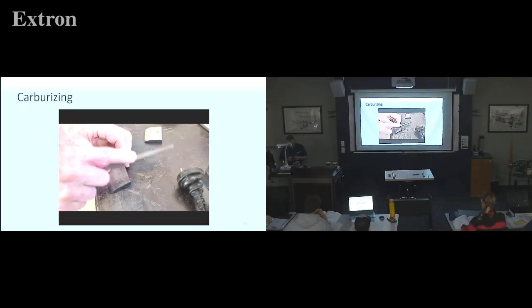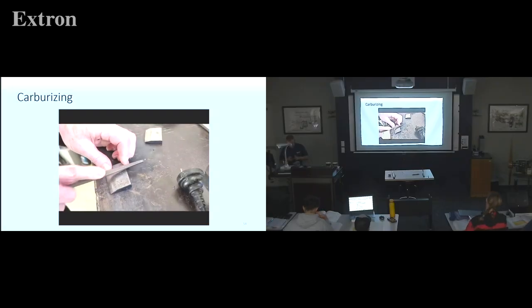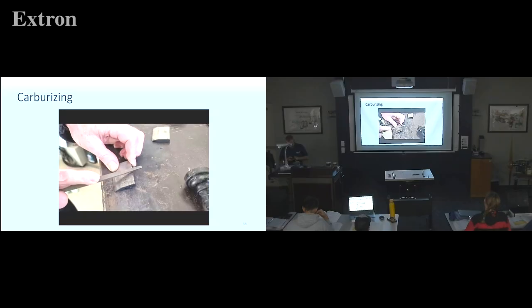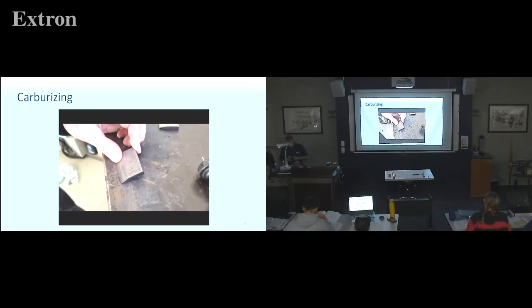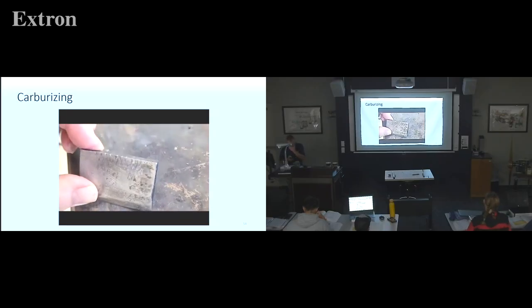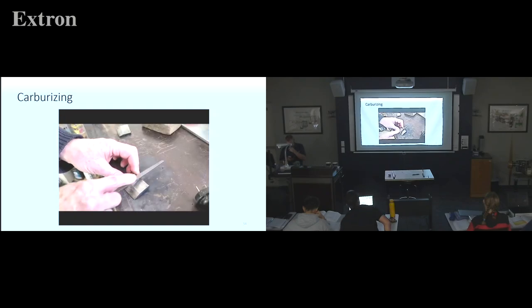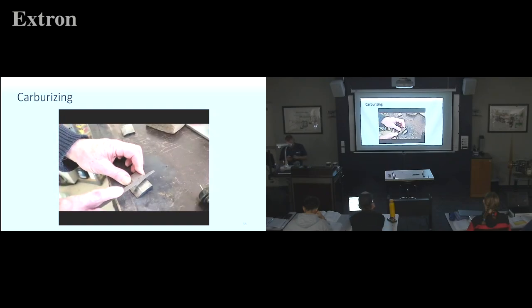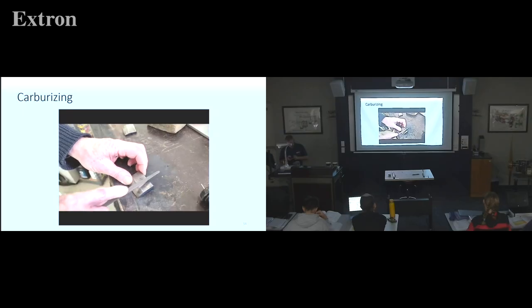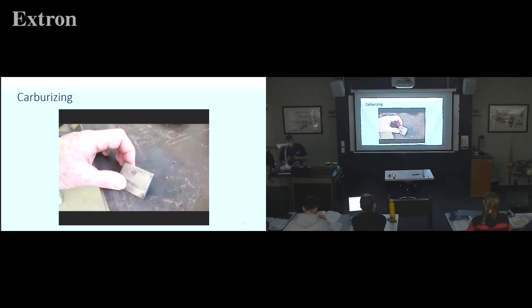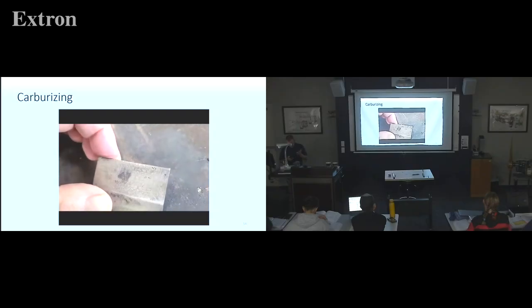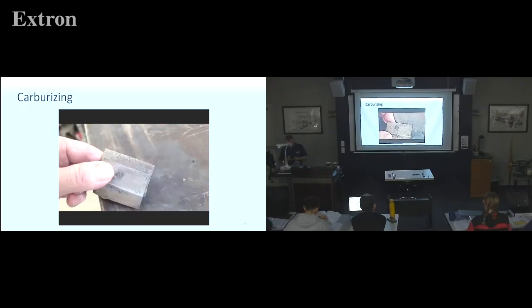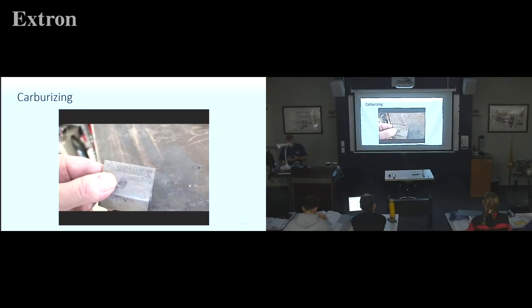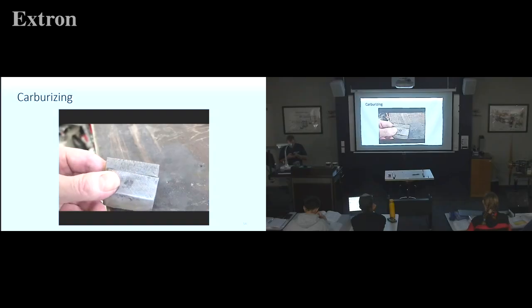Now that we have our two samples, the first test is to run a file across each sample and see how well the file can penetrate the steel. First, I tested our control sample. Then I ran the file across the carburized sample. I tried to use the same pressure and length of the strokes as I did with the first sample. Finally, I compared the file marks. You can see that the file does seem to have penetrated deeper on the non-carburized sample. So, after our first test, it does seem we've improved the steel.